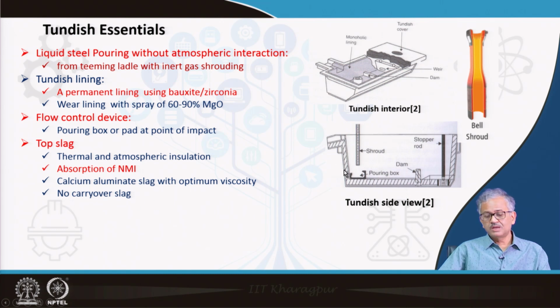And it should not contain any carryover slag, because carryover slag contains a lot of reducible oxides like FeO, SiO2, P2O5, all are reducible basically in the presence of alumina, and that is this thing. Okay.